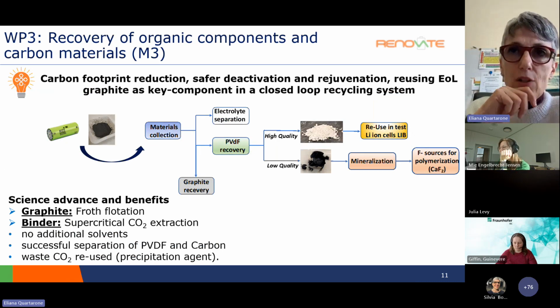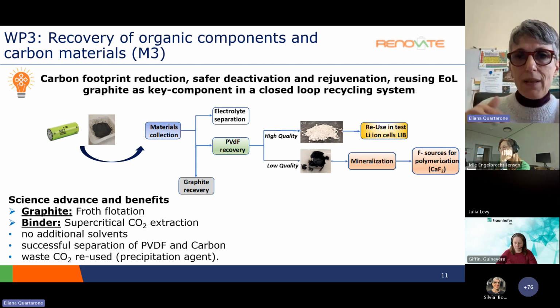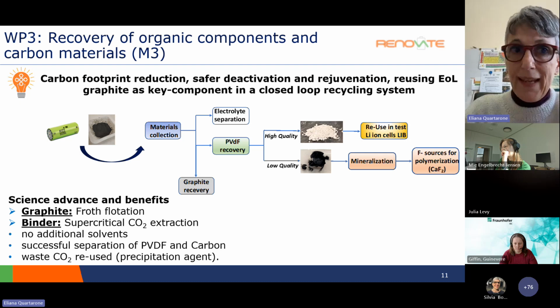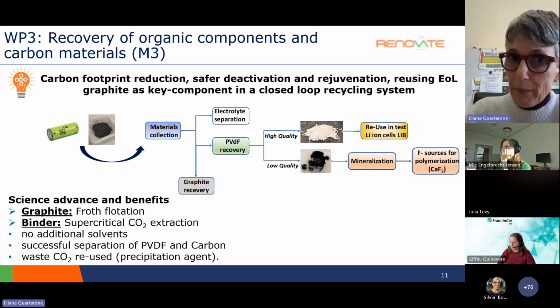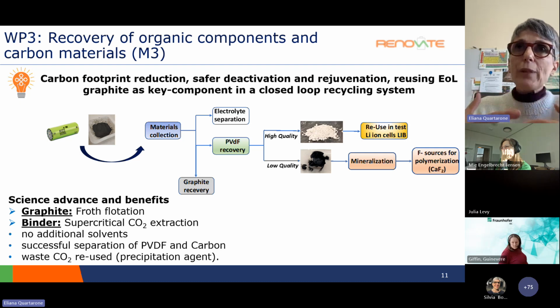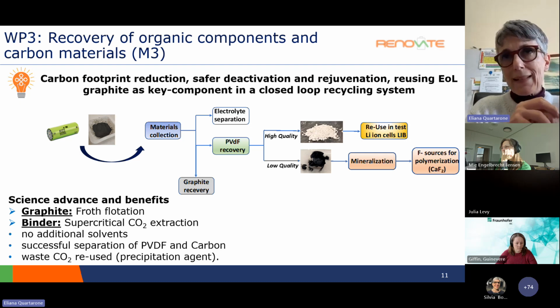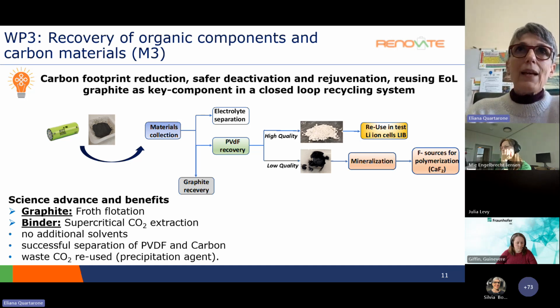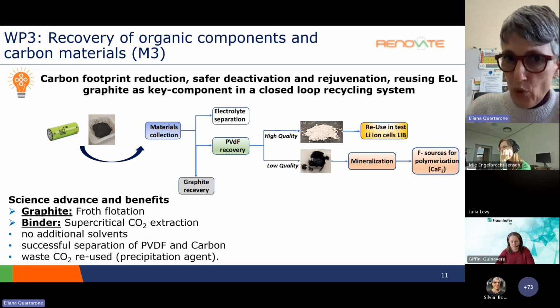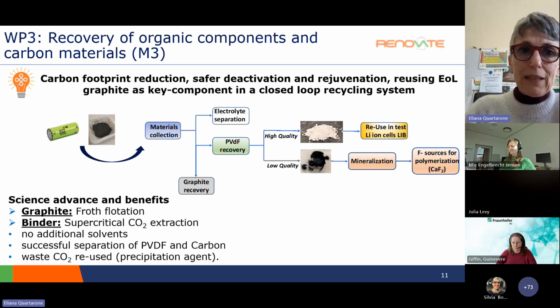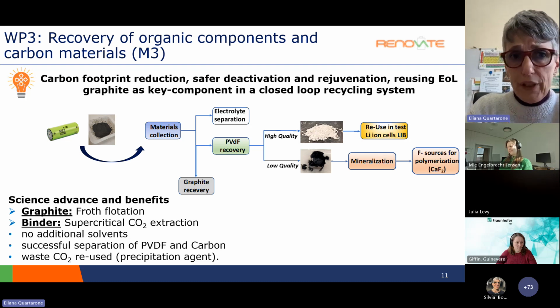Another important aspect for us is to recover the organic basic compounds in addition to the CAM. This is because there are several positive aspects that we can exploit. For example, graphite, the fluorinated binders, and also the electrolytes. Starting from the PVDF, we know that it is a fluorinated polymer which has an important value from an economic point of view, but also is a potential source of PFAS emission, and also fluorine gases or hydrofluoric acid, toxic compounds that can be obtained especially during some hydrometallurgical approaches. So it's important to investigate the possibility to recover this kind of polymer, and we are doing that by means of an innovative approach, like, for example, supercritical fluid extraction.